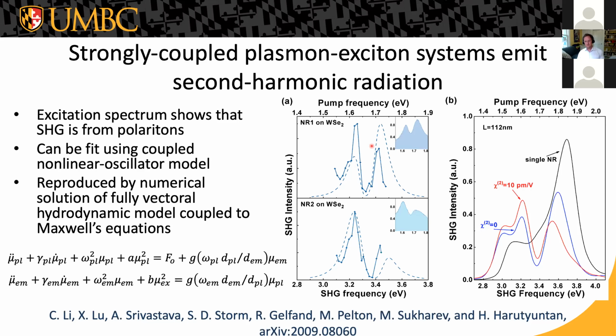Okay, so I guess the last question I would ask is, normally in the strong coupling regime, we worry a lot about relaxation to the dark states that can destroy all the effects of the strong coupling. And in your case, you need to worry about relaxation to these dark states due to the effect that the strong coupling is collective rather than single exciton. Yeah, one thing to say is that we don't see any excitation of the dark state in the second harmonic spectrum. Maxim has done calculations where if you have a really macroscopic system, you start to see a third peak show up in the spectrum at that dark state energy.